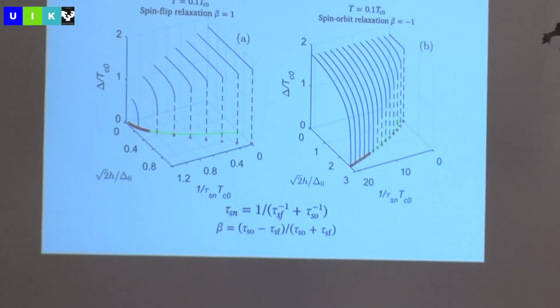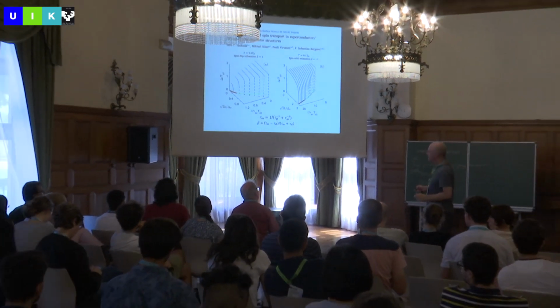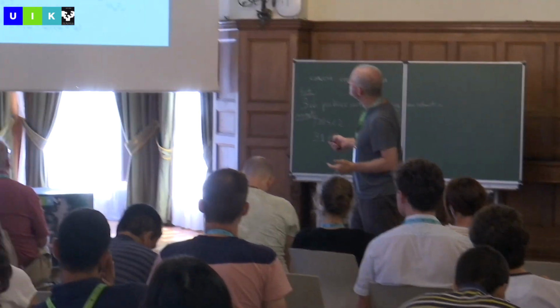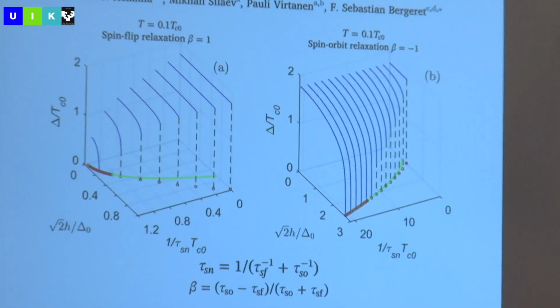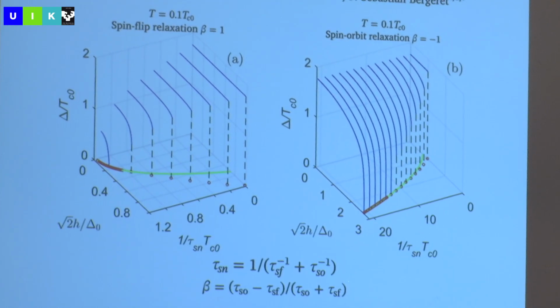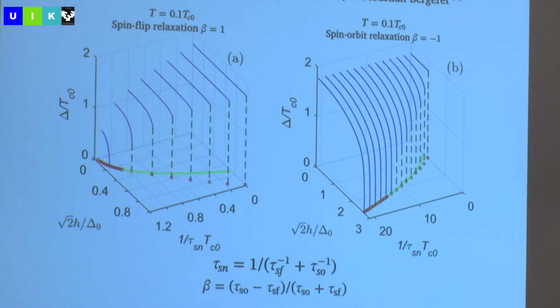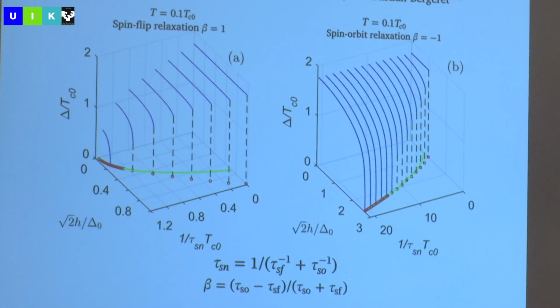If you like the theory of that subject, there's one other interesting thing. Let me just finish my sentence and then I'll stop. There are different kinds of scattering also inside of the aluminum in this case, or as in our case, the semiconductor, including spin-orbit coupling and spin-flip scattering, and all of how those affect the superconductor ferromagnetic insulator effective magnetization has been calculated theoretically. Not all of it has been measured because you don't have a knob on spin-orbit coupling often. But there's some interesting and counterintuitive things. Here's an example. This same term, tau Sn, could either be spin-flip or spin-orbit, depending on whether it's positive or negative. You see it's a difference between those two divided by the sum. So if I show you here for spin-flip relaxation by putting beta equals +1, so this is dominated by, well, maybe I got that backward actually.